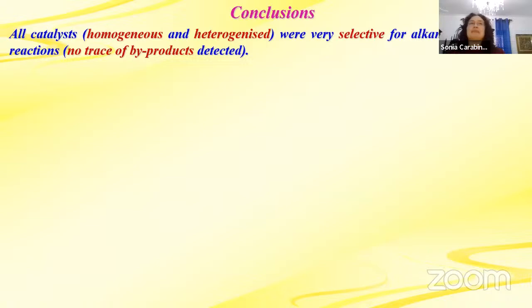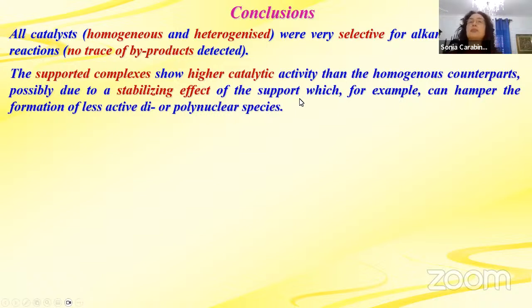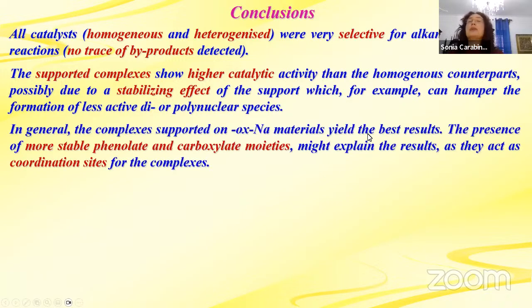Okay, some conclusions. All catalysts, heterogeneous and homogeneous, were very selective for alkane and alkyl reactions, so no trace of byproducts was detected. The supported complexes showed higher catalytic activity than the homogeneous ones, in general, of course. It's possible that there is a stabilizing effect of the support. For example, it doesn't allow the formation of dimers or other species. And also in general, the complexes supported on oxidized and sodium hydroxide treated materials gave the best results. So it's possible that these more stable phenolate and carboxylate groups give better anchoring sites for the complexes.